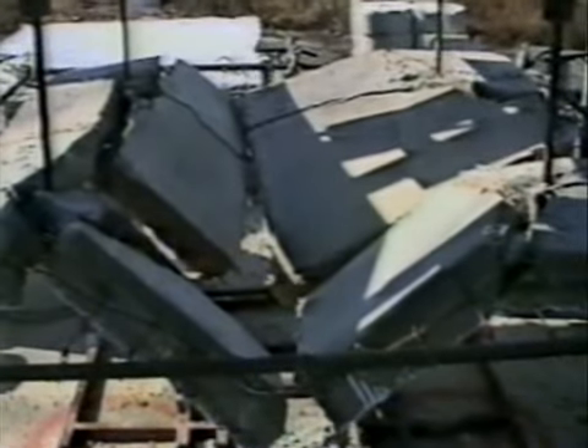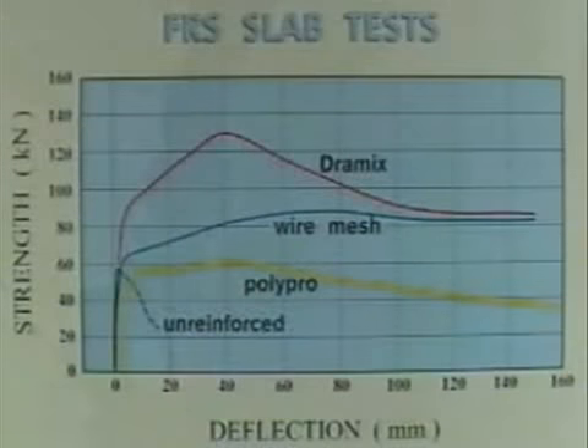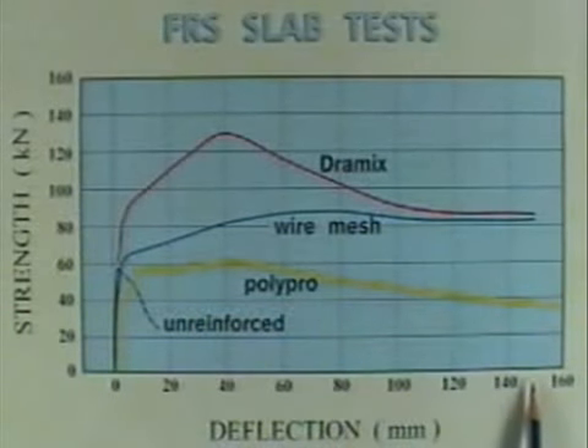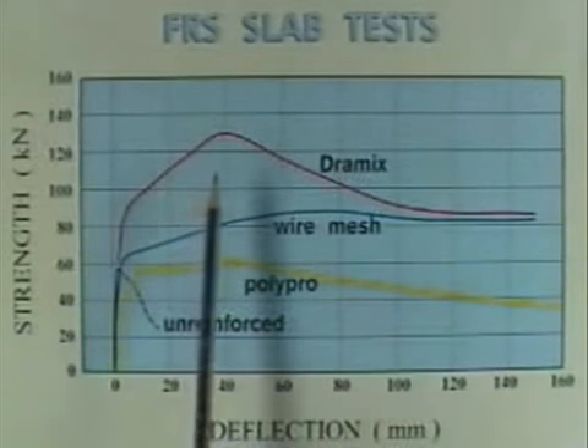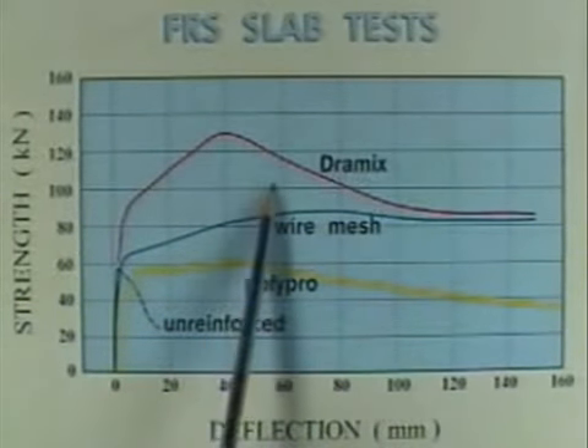During the past 2 years, the working group has conducted nearly 60 load deflection tests on large shotcrete slabs reinforced with various types, lengths and contents of fiber. From this laboratory research, the working group showed that the criterion of performance of 150 mm deflection could be met without undue loss in strength.